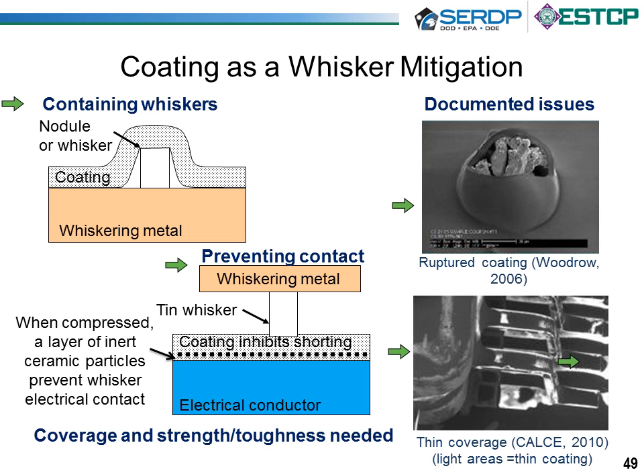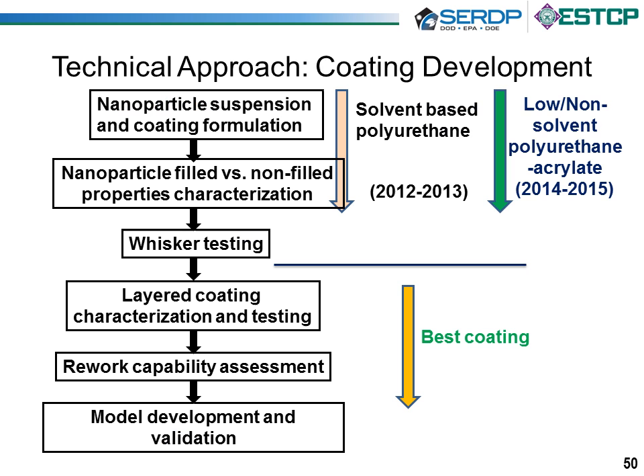Also, thin coverage. The coatings have been developed over many years for humidity protection, and now many of us are extending the role of those coatings to whisker mitigation. But the rules are different. The original material development is different. So these are some things we're trying to pay attention to. Coverage is key in trying to make sure that we don't get the coating ruptured. Of course, coating is a mitigation. If you don't want tin whiskers, don't use pure tin. But that's easier said than done when you start looking at the economics.